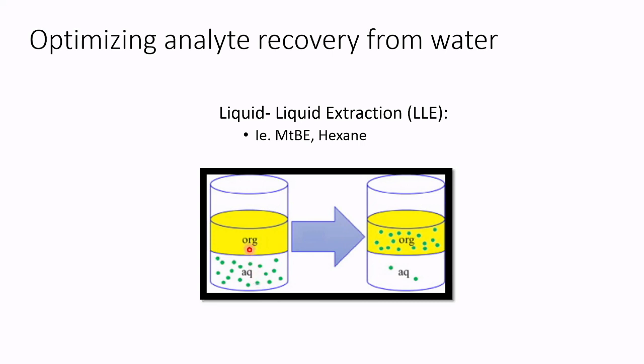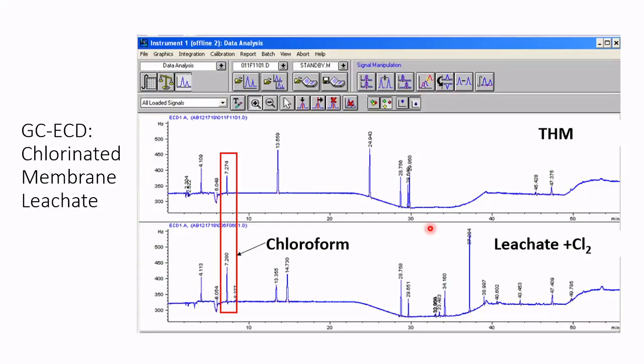So I do that by adding an organic phase, which can be MTBE or hexane, for instance. And they're not miscible. So you'll have 2 layers, and after shaking, you can get your organics to extract from the aqueous phase into the organic phase. So I can use this now to run on my GC instrument. So interestingly, when we use the GC ECD, so again, GC meaning I'm looking for volatiles, and ECD meaning I'm looking for volatiles that can be detected by the characteristic of them having an electronegative component.